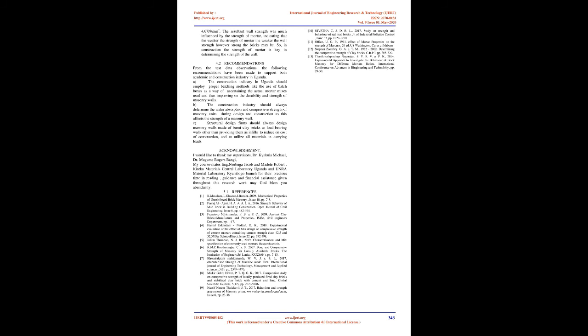4.1 Conclusion drawn from the thesis. The actual mortar mixes used on construction sites in Kampala, Uganda, have been found to be 1:7, 1:10, 1:12 and 1:14, and not the perceived mix ratios of 1:3, 1:4, 1:5 and 1:6.